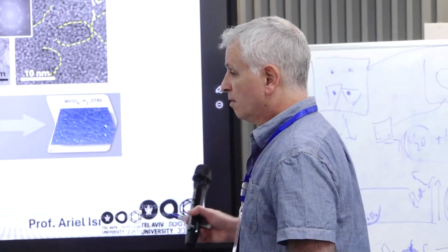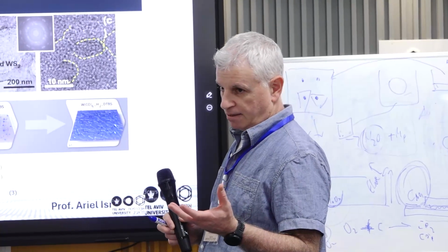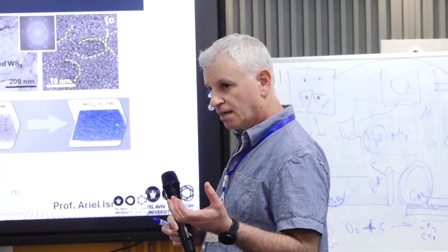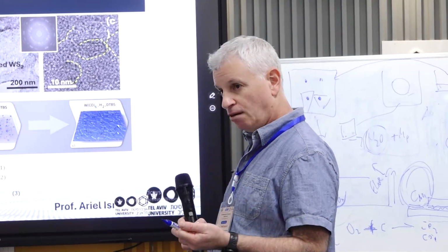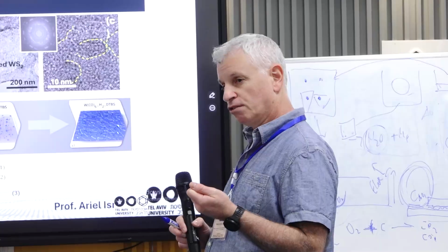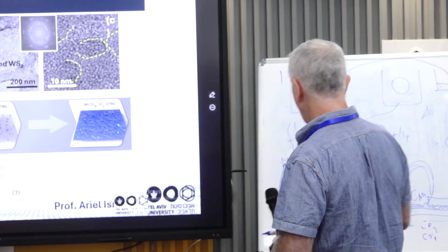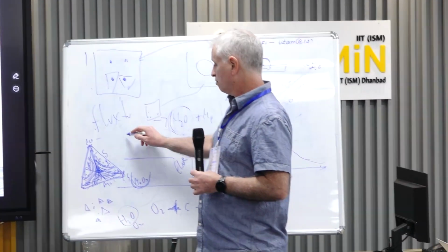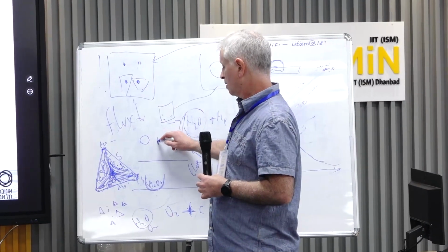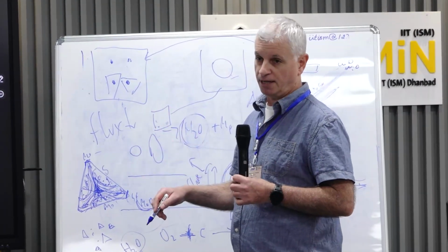Nucleation will happen only after passing the sulfur or before passing. Usually in this growth you have both precursors all the time in the gas phase. But with the metal oxide, it's very hard to control the flux of the metal oxide, so it happens a lot that you have too much of the oxide in the nucleation stage. And if you have too much of the oxide, you may end up with a lot of particles, or as I showed you, of metal oxide before they are sulfurized.